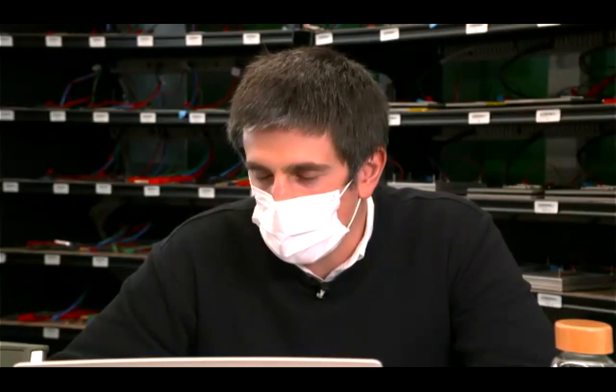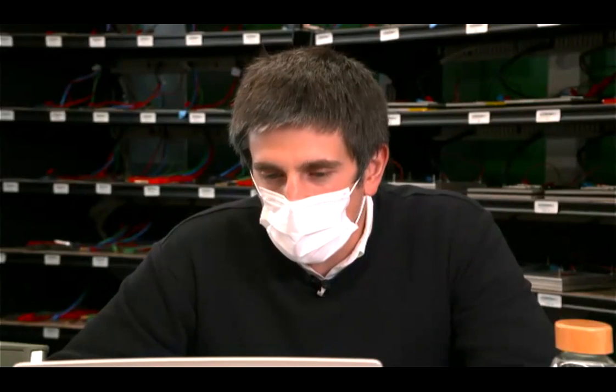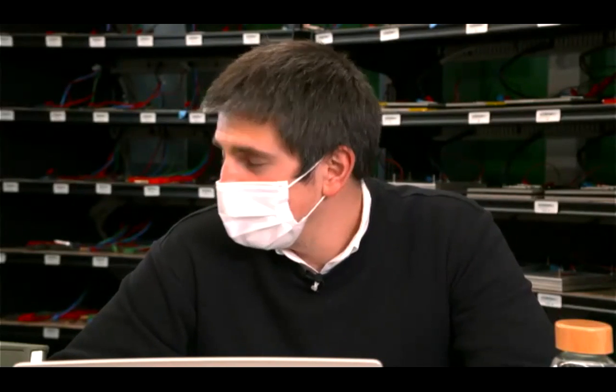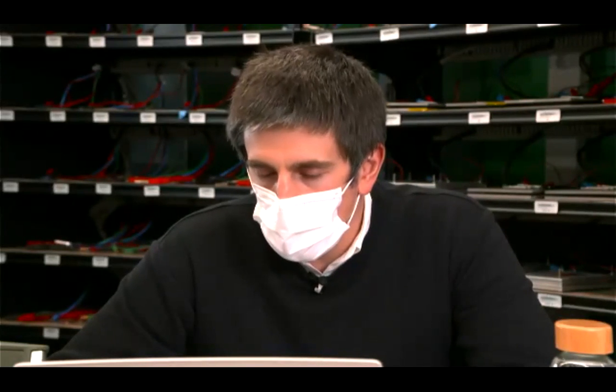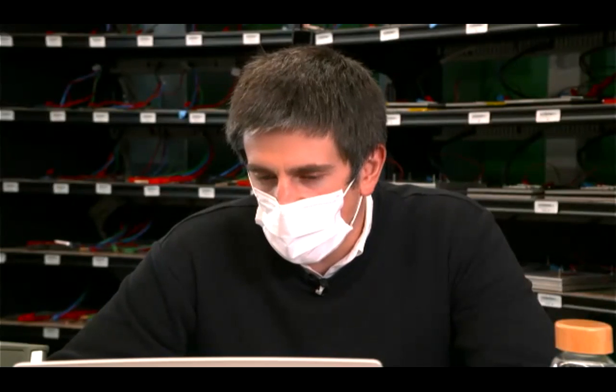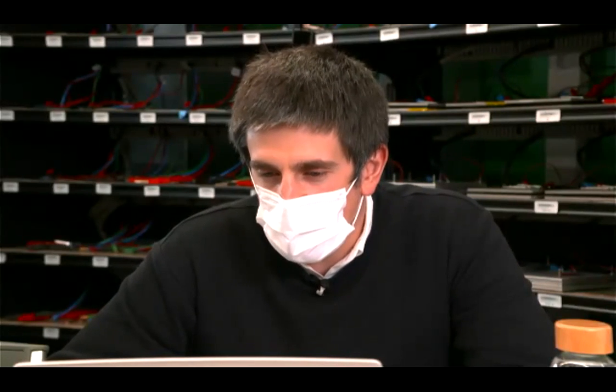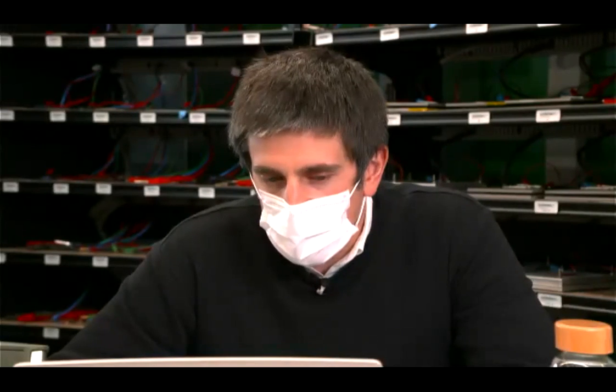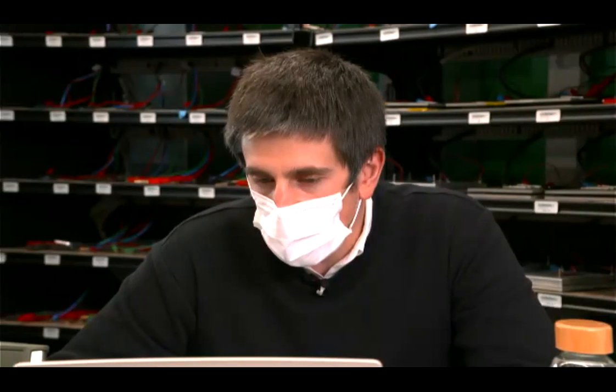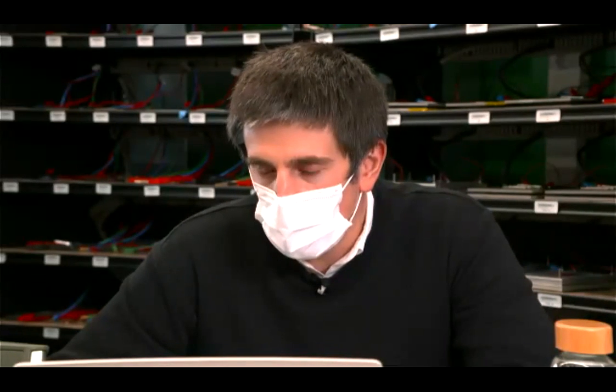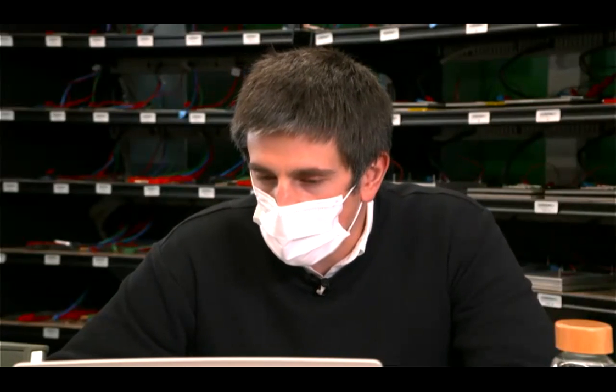And of course, for most of the cells, we are not seeing a high difference in temperature. That is something we see more, for example, in power tests, where you are using very high currents and stressing the electrodes a lot, and there you can see more of this difference in the voltage. But of course, we have this thermocouple to be sure that if we have any increase in the temperature, we have to stop the test and take the cell, because there is a problem there.